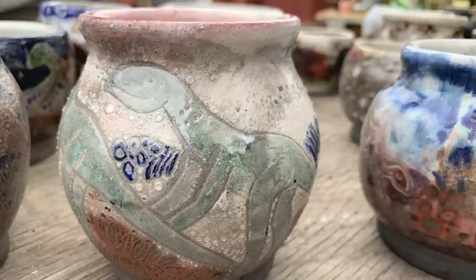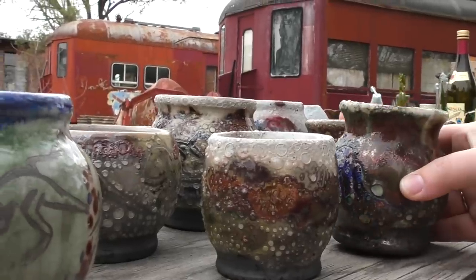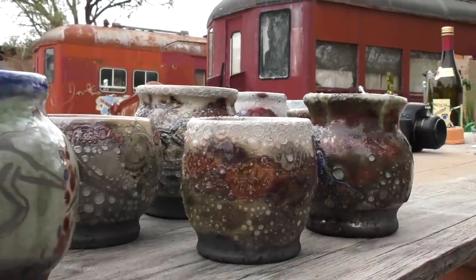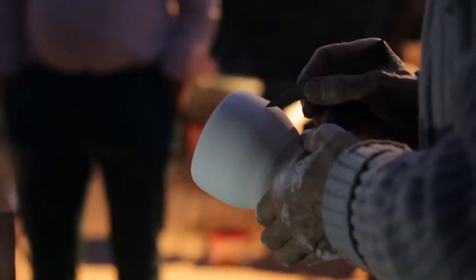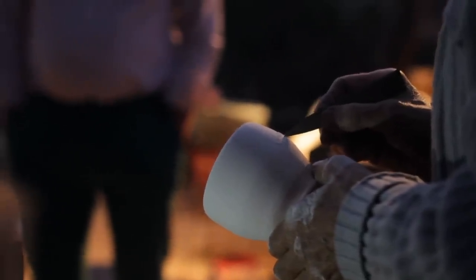I'm going to show you some of the amazing ones that did work out and came out much as expected, including these pots continuing Elizabeth Smith's sauropod series, and these peculiar bubbly oddities from the first batch - the ones that were either fired twice because the original glaze wasn't satisfactory, or were over-fired: too long in the kiln or the kiln was too hot. Several guests took their pots home at the end of the evening, so I didn't get a chance to properly film the finished products in decent light, but here are two that I have with me.